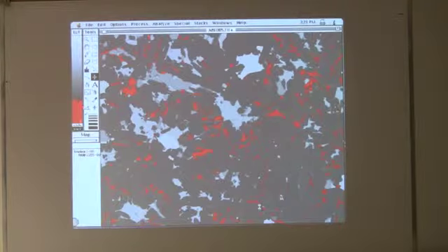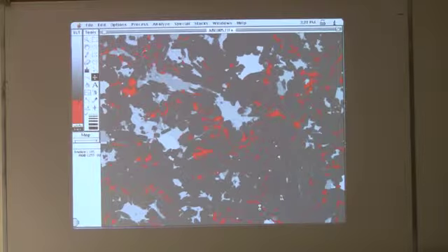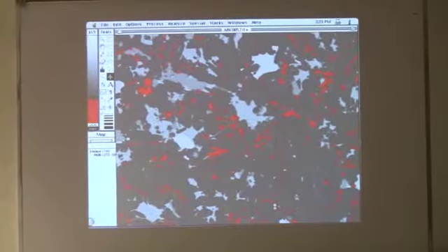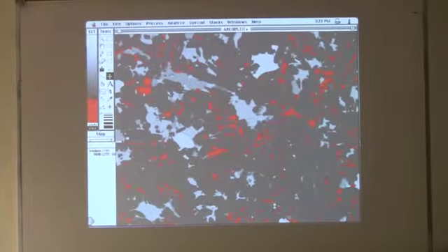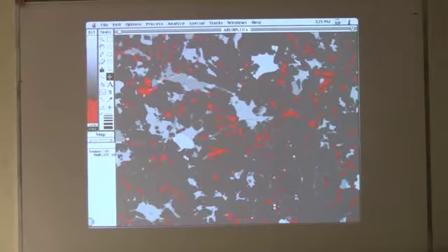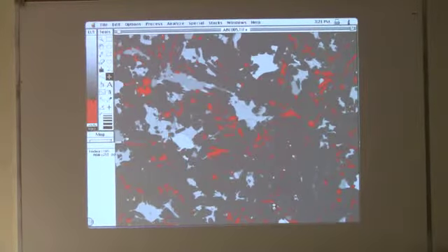Then what I do is I select the pixel range where the red fills in the cracks, and this is where the estimation of the error comes in, because I can move this selection range up and down and make the red bigger or smaller. You can't do very many at a time. Your eyes get tired. You get frustrated and fed up with it. So you do 4 or 5 images, and then you go take a break, and you come back and keep yourself fresh.